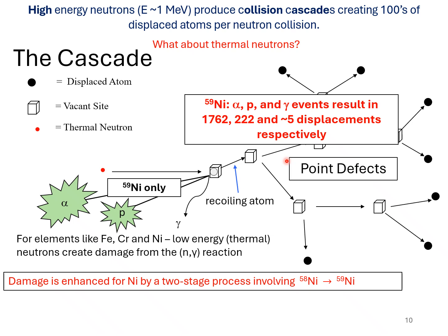Now, if that thermal neutron is interacting with nickel, the most common isotope in nickel is nickel 58, and that can then transmute into nickel 59. And nickel 59 is a very unique isotope. It has a very high cross-section for interaction with neutrons of all energies. So any further bombardment of nickel 59 with neutrons produces gamma photons. It has a high probability of producing both gamma photons, protons, which are hydrogen nuclei, and alpha particles, which are helium nuclei. It's important to realize this. The helium one I'll talk about later is very important. So because these particles are very massive relative to the gamma photon, there's a massive recoil energy, and we get a very high number of displacements for each of these events.